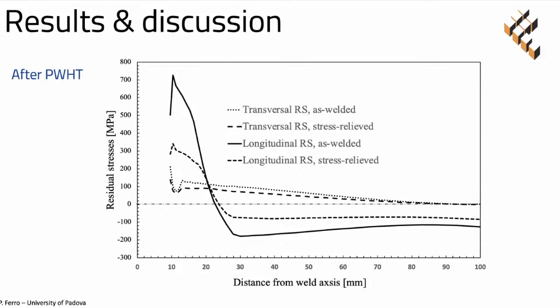In any case, with the software, we are able to calculate the distribution of residual stresses, the residual stress distribution of the as-welded joint and the stress relief joint. So we found a good variation in this case, but we didn't have the possibility right now to calculate the residual stress experimentally. But this issue was planned for the next work.